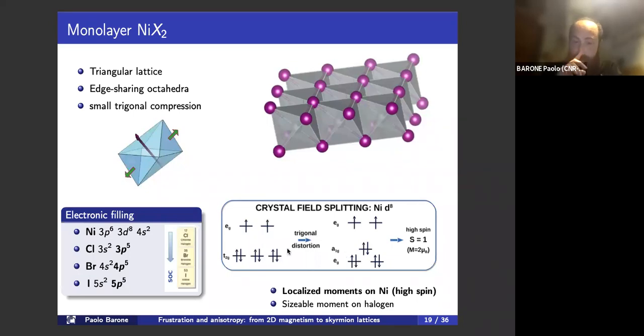The other interesting thing is that we are increasing the size of the halogen ions, at least the spatial extension of the p orbitals of this ligand. And in fact, by increasing this, we see that there is an induced moment also on the halogen ions when going from the chlorine to the iodine case. And I also remind you that the spin-orbit coupling of the nickel is the same, of course, while the spin-orbit coupling of the halogen increases when going down the column.